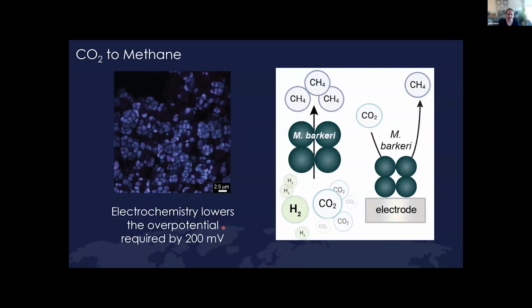I also want to note that using this protective approach, we can take microbes that generally aren't stable enough to be used in bioreactors and use them in those systems. I'm sure you've all been asking yourselves since I showed that original slide of my group why they were all dressed like cows. One of the reasons is because we use methanogens, which are microbes that can take CO2 and produce methane, and one of the strains we use has been isolated from the cow gut. What we want to do with these microbes is enable them to generate fuel materials from CO2, which would allow us to circularize the carbon economy even for tough to decarbonize industries like aviation.